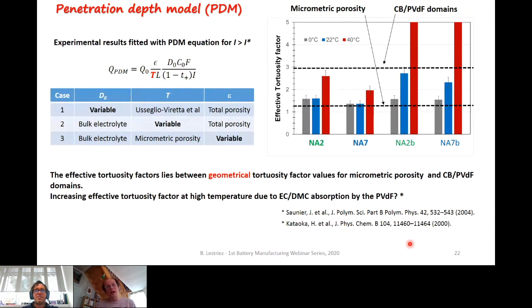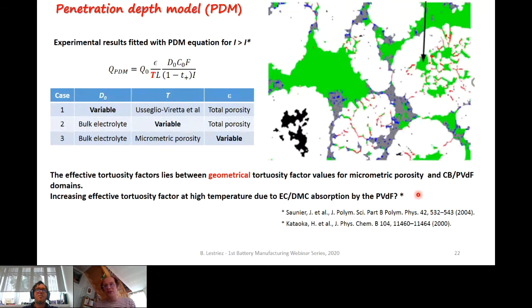So we only have an interpretation based on previous studies and also some evidence we got by doing some NMR measurements, that it might be due to the selective adsorption and swelling of the PVDF phase by the EC-DMC electrolyte solvent. The swelling can be very significant at 40 degrees C. And what we believe is that if you have a swelling of the PVDF phase, you will have an enlargement of the CB-PVDF domains, which may result in the closing of certain pores. See, for example, these micropores here or there. If you have an expansion of the PVDF domain, and a gelification of the PVDF by the electrolyte solvent, you will form there some microgels with a very high viscosity that will really hinder the diffusion of electrolyte species at this point, and thus you have a kind of loss of percolation.